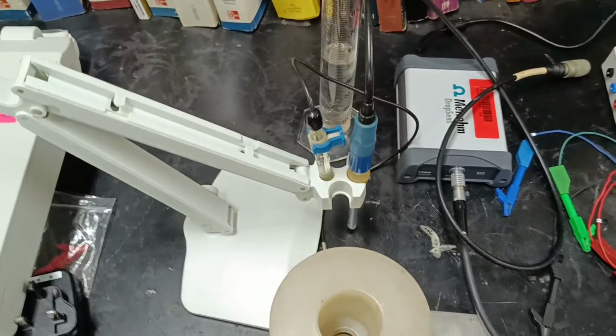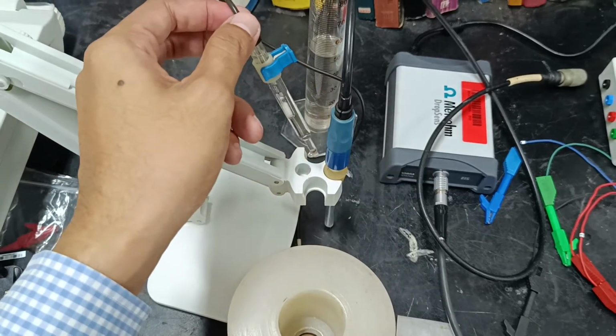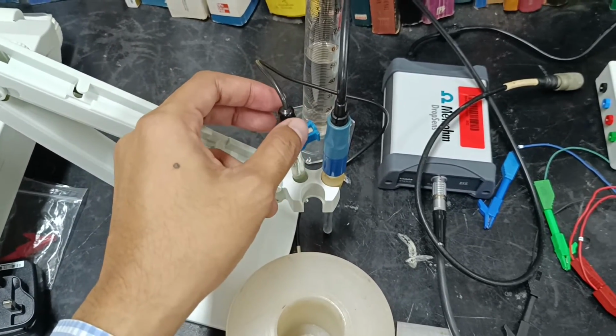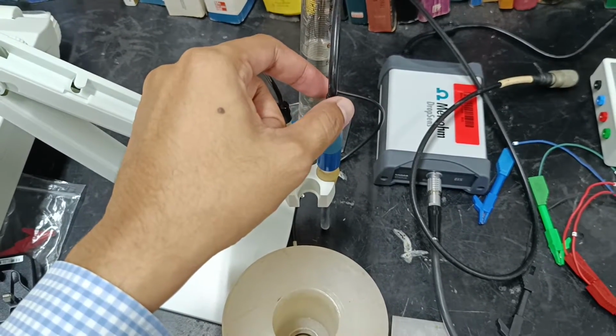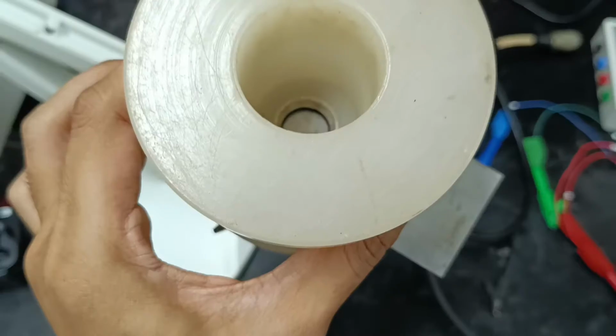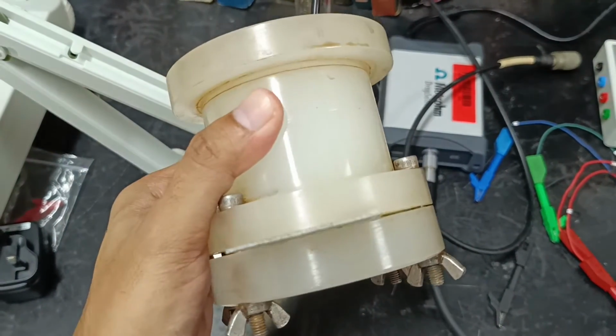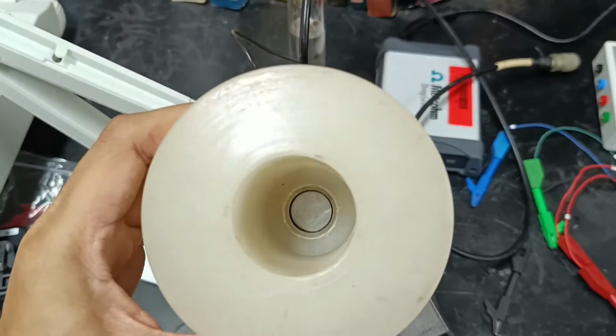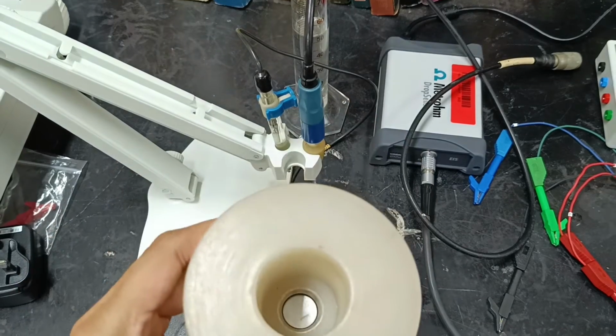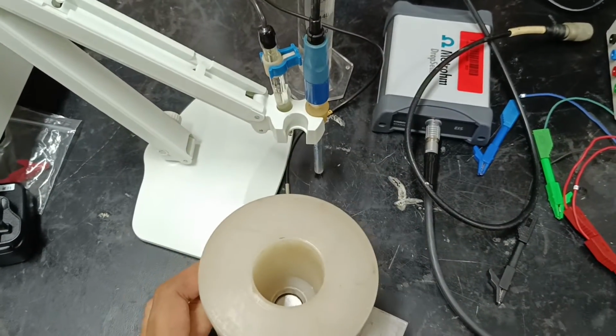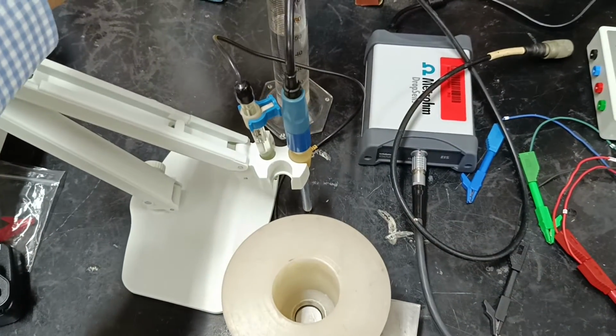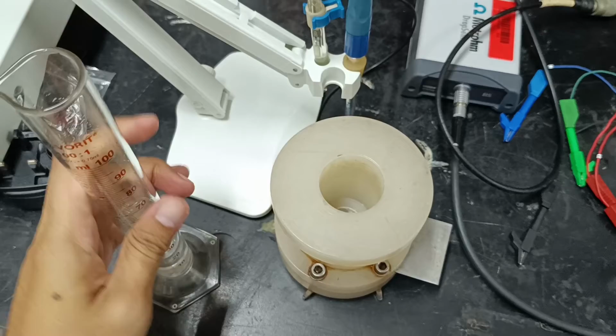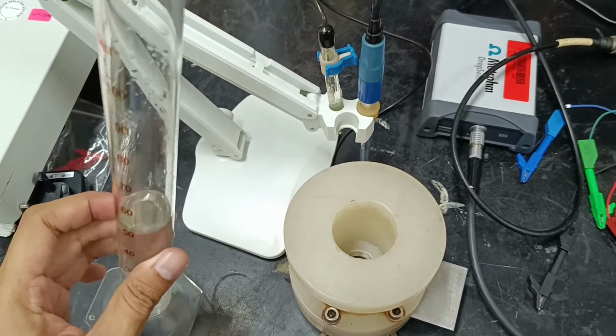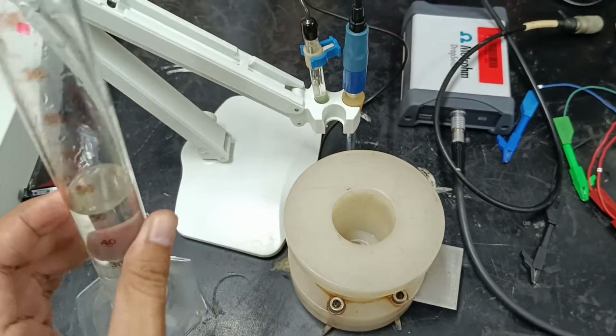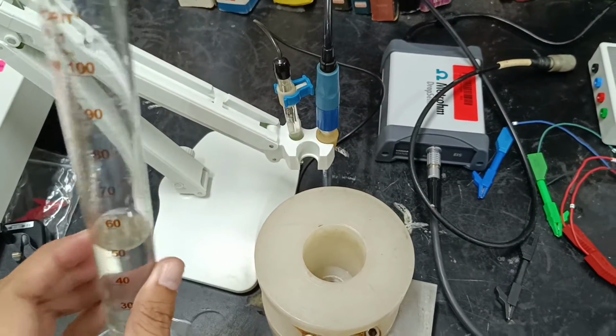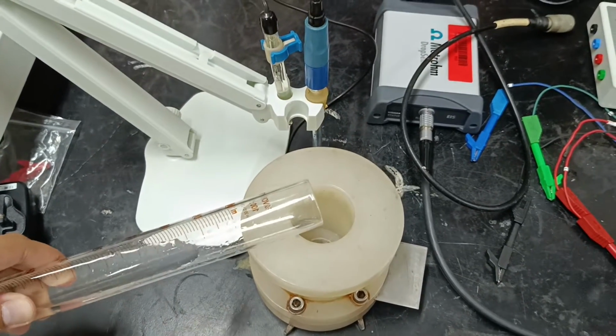So for the reference and counter electrodes, I'm going to use saturated calomel as the reference electrode, and platinum electrode as the counter electrode. So this is after I have adjusted the plates. I slot it inside, and you can see that will be the exposed area for our corrosion measurement. So I'm going to put the solution inside. The test solution is a saline solution, 3.5% sodium chloride solution. And for this cell, the volume is around 50 ml. So I'm going to pour it inside.